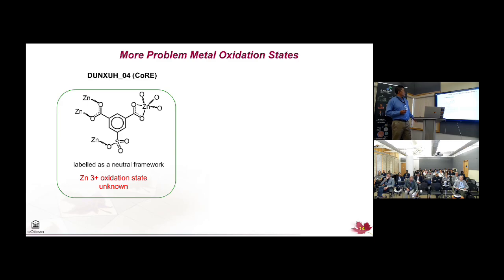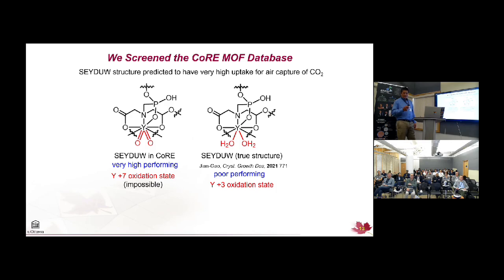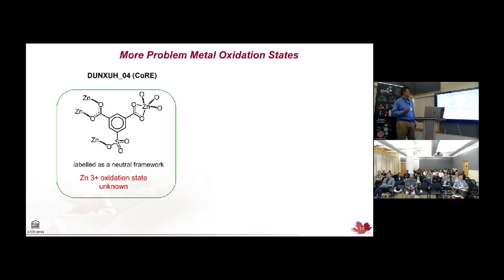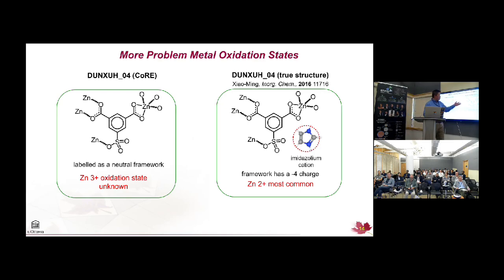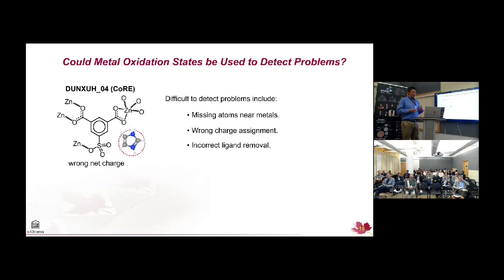So we looked at other structures, this DUNXUH structure labeled as a neutral framework. If you calculate the metal oxidation state, it's +3. That's basically unknown in MOFs. Again, we went to the original paper, and it turns out they had removed the counter ion but not accounted for the charge. So the framework actually has a -4 charge, and then if you do your electron counting, it's happy in its +2 oxidation state. So we started thinking metal oxidation state could be used to detect problem structures, because in this case with DUNXUH, there's nothing wrong with the bonds. Bond distances are all normal. Everything's fine. It just was mislabeled.